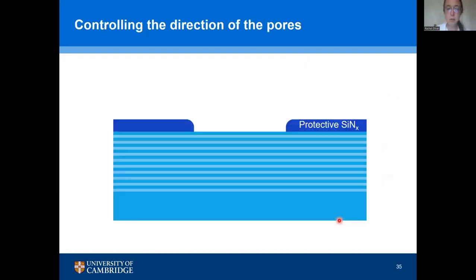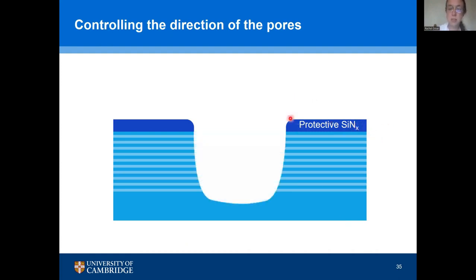The other thing is that having discovered this birefringence effect, we realized we could control it. Now I have to say here, we're swapping from our dislocation-based approach to etching these samples into an approach much more similar to the original way that porous gallium nitride was made, with lithographic steps. We've put down protective silicon nitride on the surface. We use a reactive ion etch to take away a big trench of material, and then our porosification is going to happen from those trench sidewalls out rather than through defects. But the idea here was that by etching in this radial fashion, we could control the direction of the pores.